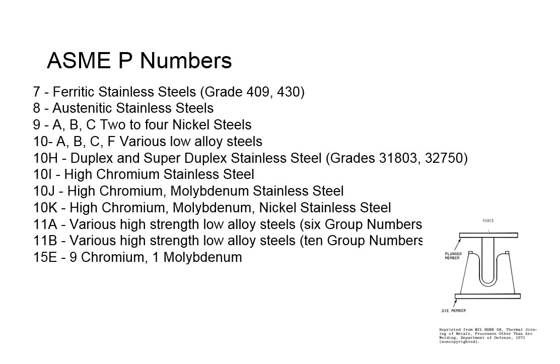The other one we want to look at here is 15E, which is 9 chromium, 1 molybdenum. These are getting to be more popular in steam power plants, and these are creep-resistant materials. Creep strength enhanced ferritics, I think is what they are, CSEF. But these things are pretty onerous. You've got to have the preheat right. You've got to have the post-weld heat treat right. There's an intermediate post-weld heat treat that you've got to have in there and done correctly.